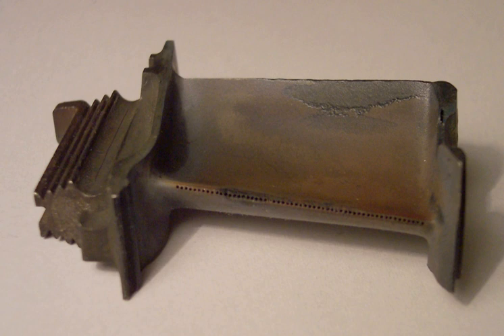The creep deformation behavior of superalloy single crystals is strongly temperature, stress, orientation and alloy dependent. For a single crystal superalloy, there are three different modes of creep deformation under regimes of different temperature and stress: rafting, tertiary and primary. At low temperature, approximately 750 degrees Celsius, SX alloys exhibit mostly primary creep behavior. Matan et al. concluded that the extent of primary creep deformation depends strongly on the angle between the tensile axis and the symmetry boundary. At temperatures above 850 degrees Celsius, tertiary creep dominates and promotes strain softening behavior.